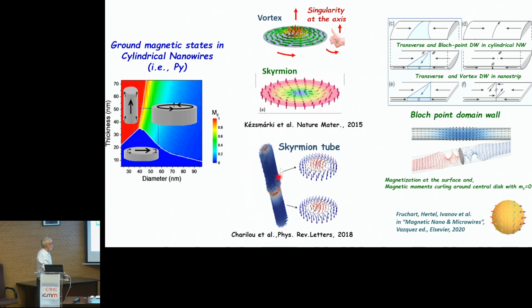But what happens in the case of our nanowires? In our nanowires, we can observe what is called a skyrmion tube. So we have this skyrmion that extends along the length of the nanowire. Most of the work on skyrmions has been done from the theoretical point of view, but very recently we have been more or less confirming this skyrmion structure. But I would like to point out the difference between nanostrips and nanowires. In nanostrips, we can have a transverse domain wall separating two axially magnetized domains, or this vortex structure. In cylindrical nanowires, we can also have these transverse domains, similar to the strips, but very differently, this vortex actually becomes a Bloch point domain wall.